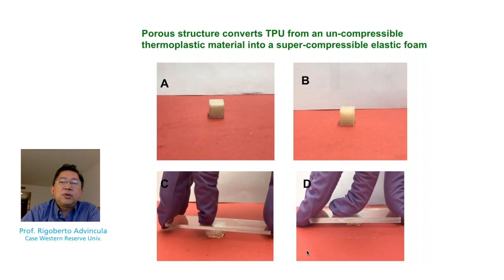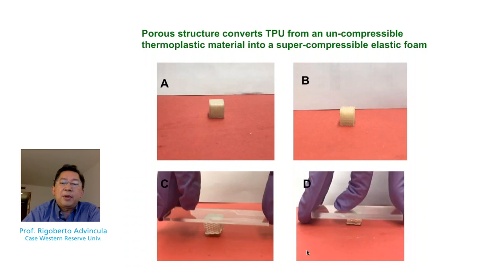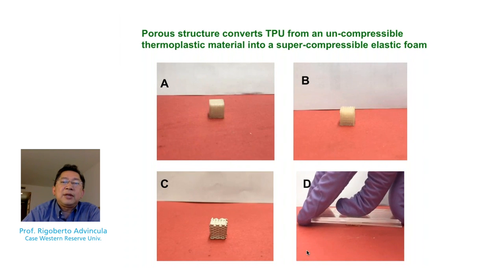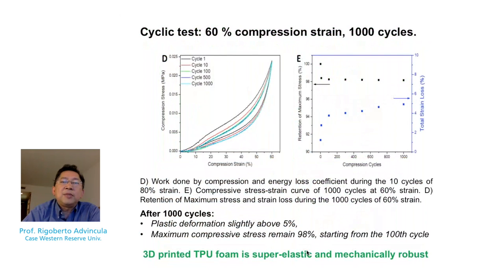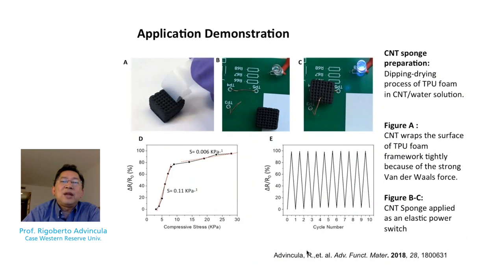Okay. So from here, why am I showing this and why is this a good example of an electronic? So actually we took this material, it showed various compressibilities up to 1,000 cycles. But interestingly, when we coat it with a conductive material such as a carbon nanotube containing paint, we can actually use it as a switch, an LED switch in a printed circuit board. So by turning it on and off, the 3D printing allowed us to change the thermomechanical properties and made for it a very durable switch for turning the LED.